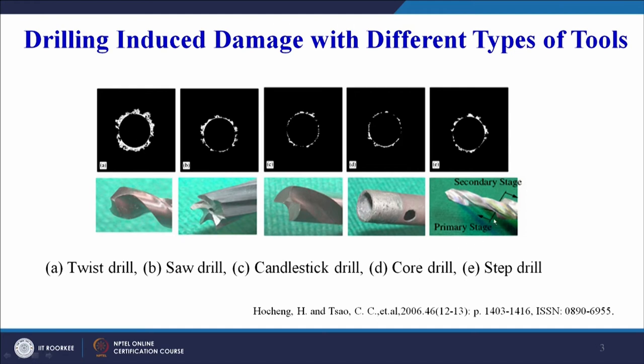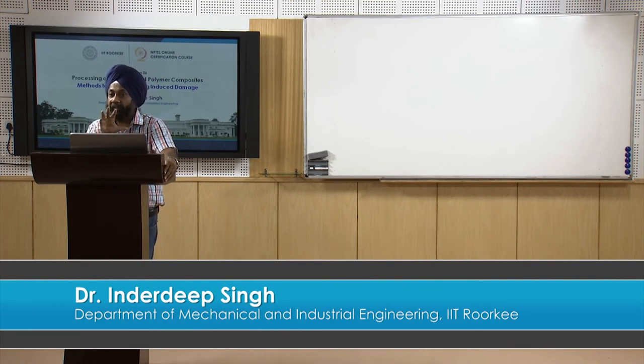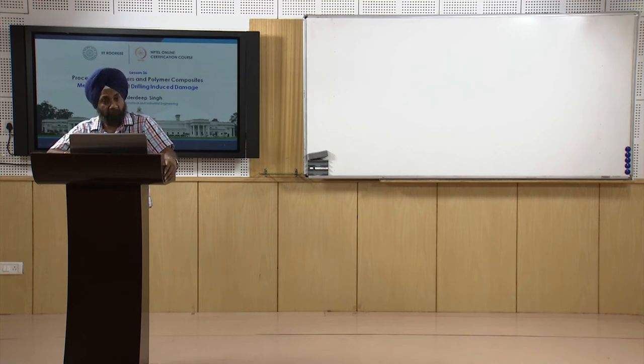Visually, the core drill appears to lead to minimum damage around the hole. To scientifically quantify damage, we can use non-destructive dye penetrant testing or ultrasonic C-scan to observe the area around the drilled hole. This establishes the importance of tool point geometry as a key criterion for defining damage around drilled holes. We should appropriately and intelligently select the drill point geometry so that damage in polymer matrix composites is minimized.